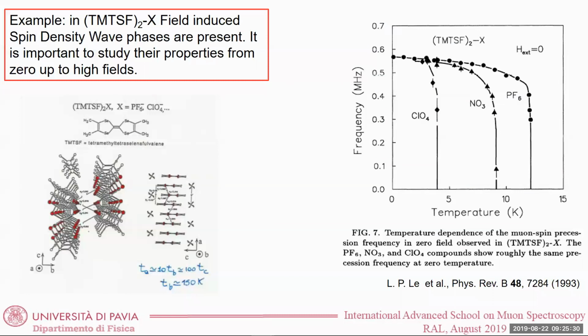Another example: these are a family of organic conductors which goes under the name of Bechgaard salts. So you have a quasi-one-dimensional organic conductor where you have a stacking of these TMTSF molecules, which gives rise to a high conductance along this direction. And what happens at low temperatures is that in these systems, you can have a spin density wave phase or a superconducting phase. The point is that in certain of these systems, this superconducting phase can be quenched, and you can have a spin density wave phase which is induced and strengthened by the magnetic field. So the magnetic field is affecting the ground state of the system.